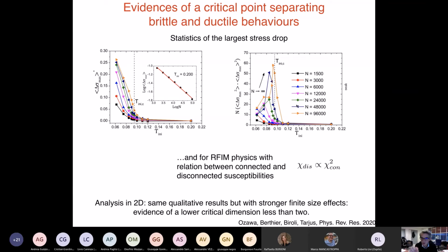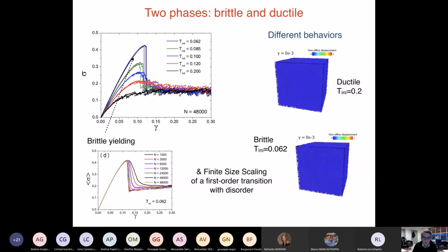Is the fluctuation of the order parameter due to the disorder. And this fluctuation actually diverges at the critical point, where the critical point is the point at which delta sigma goes to 0, so you go from this discontinuous behavior to the continuous behavior.